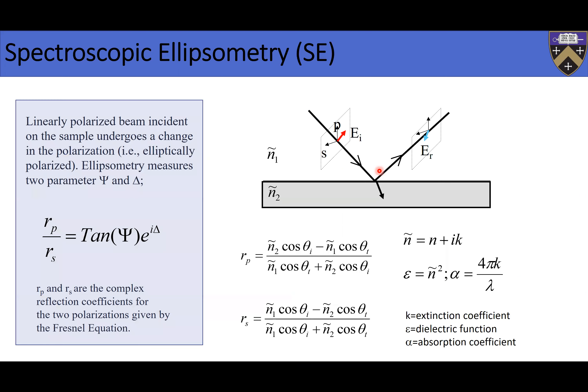Let's sketch the physics of the problem. Let's assume you have a sample with a complex index of refraction. The complex index of refraction has the ordinary index of refraction you're used to, plus a complex part. For glass, n = 1.5 and the extinction coefficient K is zero — that's why we only give one parameter. Otherwise, you need two parameters to define the complex index of refraction. If I take the square of that, it equals the dielectric function. These are all complex numbers, and the absorption coefficient is proportional to the extinction coefficient.